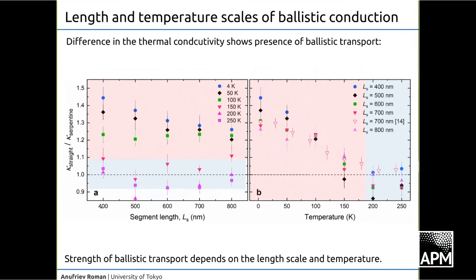And we can see that indeed, as we increase segment length, the points tend to go down. So at the scale of 400 nanometers, ballisticity is stronger than at the scale of 800 nanometers. And the same happens on the temperature scale. As we increase temperature, all points tend to go down. And above something like 200K, we were not able to detect any sign of ballisticity using this more direct method of probing. So the conclusion could be that we could not directly probe any sign of ballistic conduction on the scale of 400 nanometers, but in a previous experiment, we could still feel some weird resistance even at room temperature.